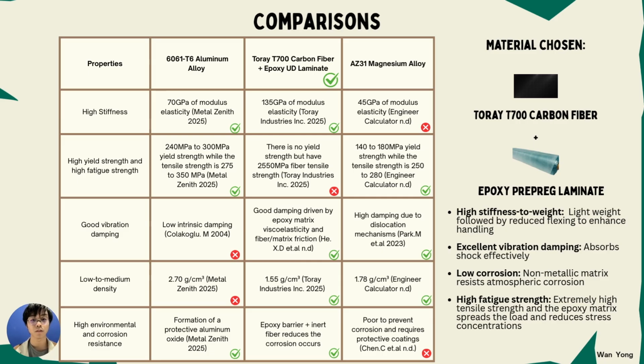Next we talk about the strength and the fatigue performance, which also show a major difference. The aluminum has a yield strength between 240 and 300 megapascals, and magnesium is lower at 140 to 180 megapascals, whereas the carbon fiber inside the composite exhibits extremely high tensile strength, around 2550 megapascals.